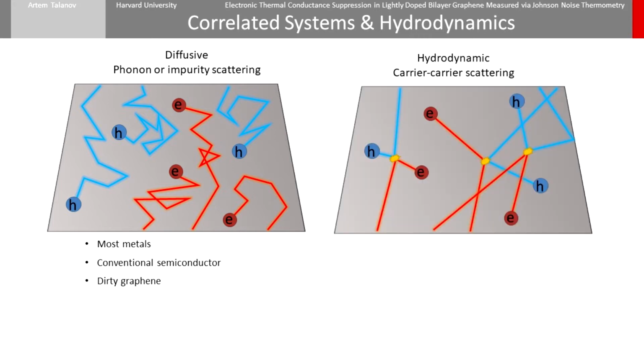This is the transport we typically consider in most metals, conventional semiconductors such as silicon, and dirty graphene. However, what happens if we can make our sample cleaner to remove impurity scattering, and we can lower the temperature enough to kill off phonon scattering, but not so low that we also kill off electron-electron scattering? We enter the hydrodynamic regime, where carrier-carrier scattering becomes the dominant collision and relaxation mechanism. The particles no longer follow independent random walks, but are now highly correlated and move as a collective fluid.